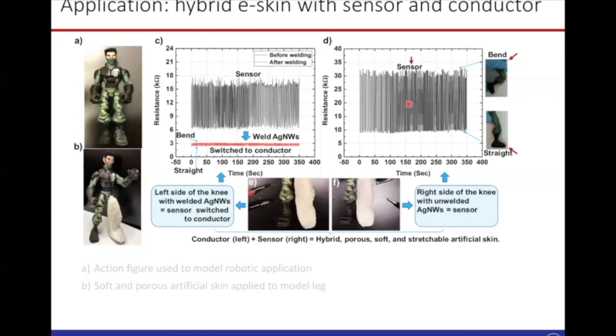And you have similar behavior on the electrical network on the left side. Then we apply a voltage between this network on the left side, meaning that we're trying to weld the silver nanowire, and the behavior changes. The sample becomes more conductive and the gauge factor is also suppressed. So this red curve behaves more like a conductor. The black curve before welding was more like a sensor.